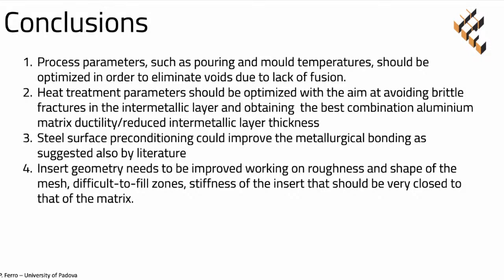So the main conclusion, in my opinion, is this. This is the point zero of this work, in which we can find different improvements that we can obtain in future works. In particular, we can increase the pouring temperature in order to increase the fluidity of the alloy and reduce the lack of filling defects that are the main cause of the low mechanical properties we found in the compound casting.